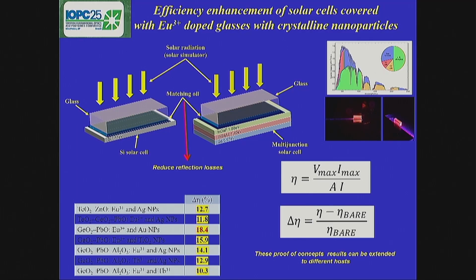We use different solar cells, a commercial silicon solar cell, and also a multi-junction solar cell that is formed by layers of semiconductor materials. This solar cell has aerospace applications. We cover the solar cell with our glasses, and we use an immersion oil at the interface between the glass and the solar cell to reduce the reflection losses and improve the optical match. Then we perform the electric characterization. We mainly use europium ions due to the strong red light that is emitted at about 600 nanometers.